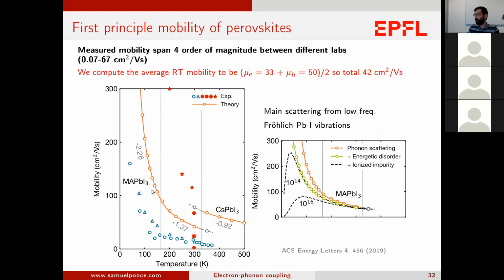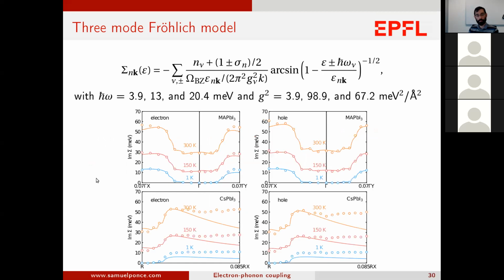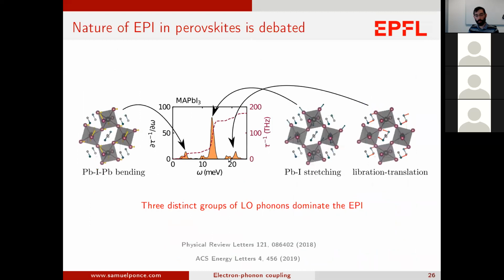Sure. I was just thinking about these 3 parameters, trying to get a physical meaning. 20 meV is more or less 160 cm⁻¹, which is purely on the side of the libration of the organic cations, if I make it for lead iodide at least. Totally, this is this mode. Yes, you're exactly right. This is 20 meV, which corresponds to the libration and translation of the organic molecules.